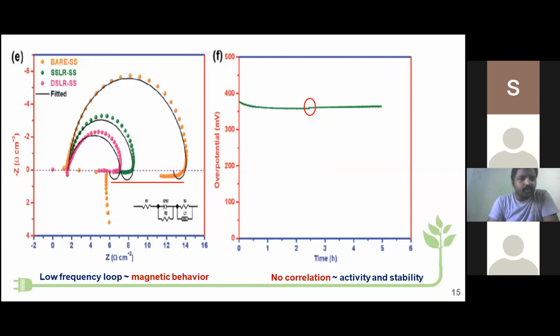In addition to that, all three Nyquist plots show an inductive loop at low frequency, which is highlighted by means of a red line, and which arises due to the magnetic behavior of the materials. So the bare stainless steel also has magnetic behavior, but after laser radiation, its magnetic behavior is enhanced.